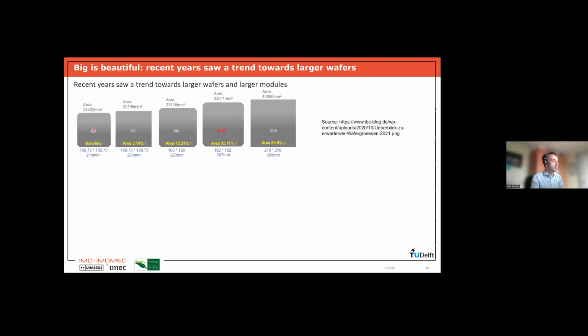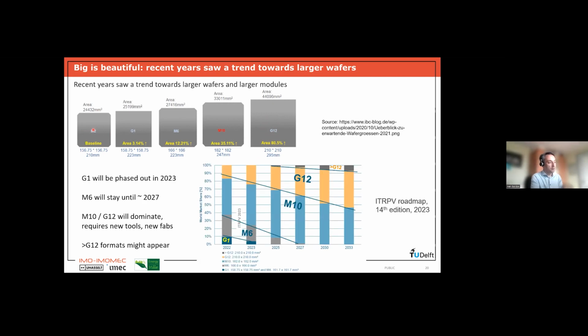And if we look again to the ITR-PV roadmap, to the present situation, today, 2022, 2023, we see that different sizes are being used by the industry. So there is not one standard at the moment, but almost nobody is still using the very small wafers anymore. Until 3-4 years ago, everybody was using these G1 wafers, and now almost nobody is using them anymore. In the next couple of years, these largest wafers, the M10 and G12, will really start to dominate. And some people even expect that perhaps the wafer size will become even larger, but that is not so sure.